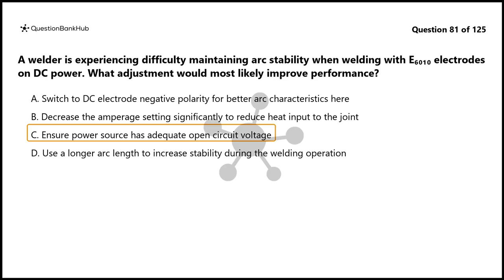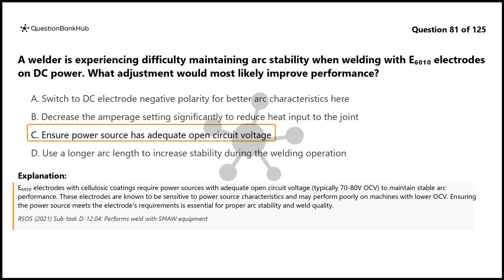The correct answer is C. Ensure power source has adequate open circuit voltage. E6010 electrodes with cellulosic coatings require power sources with adequate open circuit voltage, typically 70 to 80 volts OCV, to maintain stable arc performance. These electrodes are known to be sensitive to power source characteristics and may perform poorly on machines with lower OCV. Ensuring the power source meets the electrode's requirements is essential for proper arc stability and weld quality.